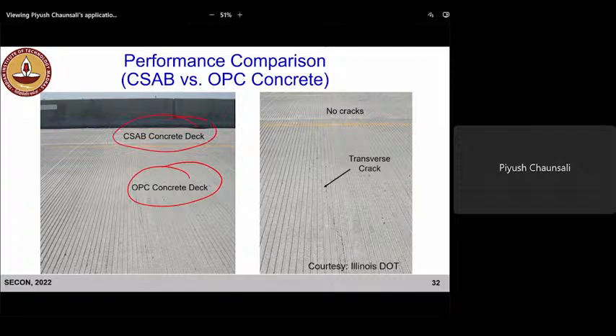So this is the final image, and we then looked at the cracking pattern. So you see here there were cracks in the Portland cement concrete deck. Again, this is because of the shrinkage. Concrete tries to shrink but is restrained. There is tension, and when the tensile stresses exceed the tensile strength, the concrete cracks. That happened in the Portland cement deck, but these cracks didn't appear in the CSAB concrete. So this was the performance comparison between CSAB and Portland cement concrete. As far as resistance against shrinkage cracking is concerned, this cement is a solution for that.